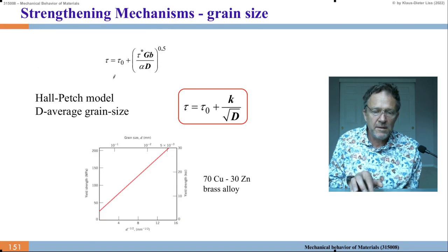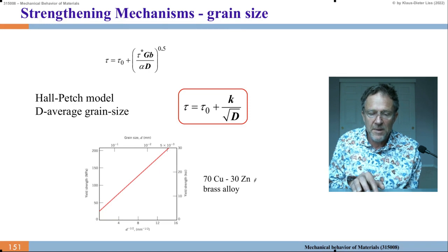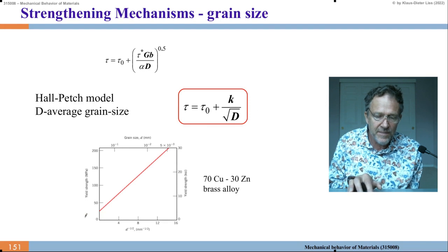So we can plot it. The equation is here again: tau equals tau 0 plus k over square root of D. And this is the Hall-Petch model, where D is the average grain size. For copper 70% and zinc 30%, a brass alloy, the data is shown here. This is literature data based on experiment, and here is the square root of 1 over D, and that has a very linear behavior. Here's the yield strength in megapascal. If we go to 0, then we have the initial yield stress tau 0.